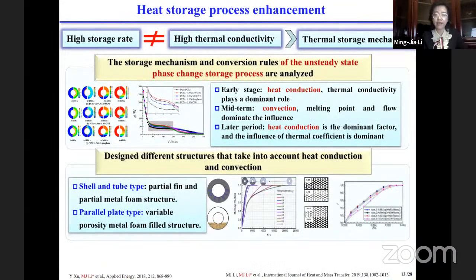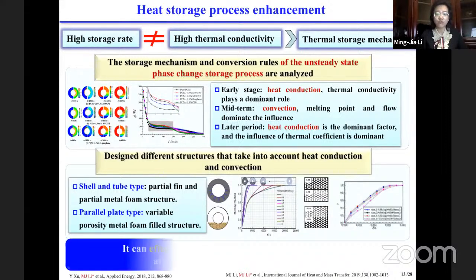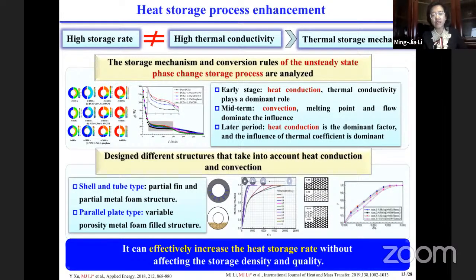We also need to enhance the thermal storage process, but we know a high storage rate doesn't mean high thermal conductivity. So that's why we need to understand the mechanism. We studied the storage conversion rules of the unsteady state phase change storage process from both the heat conduction and heat convection sides. We also designed different structures in order to improve the performance. As a result, we highly increase the heat storage rate without affecting the storage density and quality.